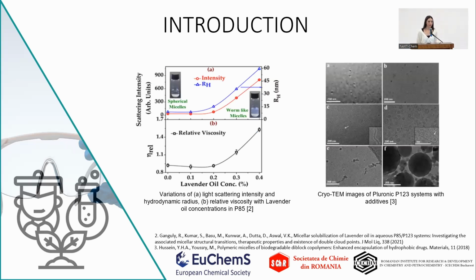There are many studies involving pluronic micelles encapsulating essential oils. One of these studies refers to pluronic P85 encapsulating lavender oil. In this study, the authors managed to correlate the relative viscosity of the dispersion, the light scattering intensity, and the hydrodynamic radius of the aggregates with the transition between the spherical micelles and the worm-like micelles. On the right side of the slide, there is a micrograph of a system of pluronic P123, in which there is an outlined transition from the spherical shape right here to an elongated shape, and further to much bigger aggregates.